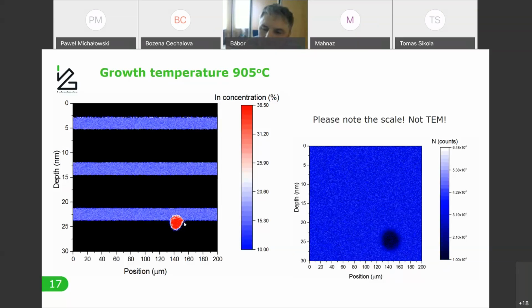It actually requires a lot of time, because to be sure that this beam is so small and still homogeneous, I was recording a lot of parameters to go back to, and I made craters with these different sets of parameters. Then I was removing the sample and checking with AFM whether the crater is flat or not. The first step to optimize really took me like 2 or 3 months. But with changing these parameters, I started to know which parameters are very important and which not so much. With this knowledge, I was finally able to optimize it.